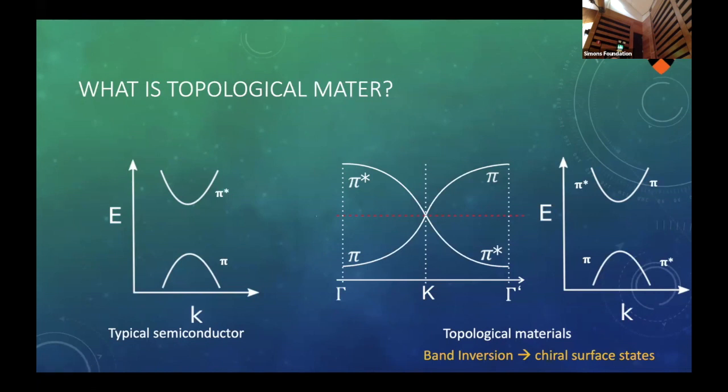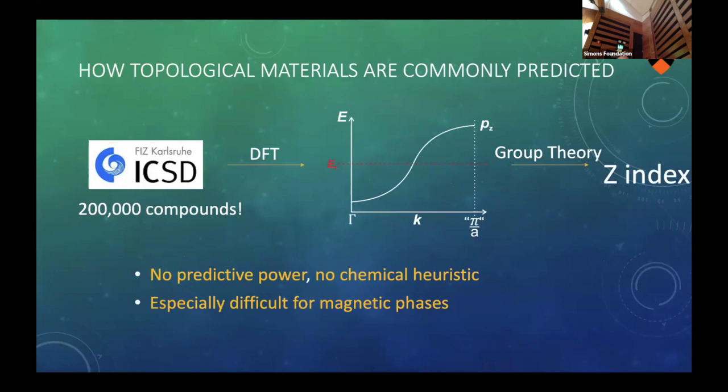And I just want to make sure that for the remainder of this talk, when I define this, I view a band inversion as being the basis for topological materials, because spin orbit coupling can come in later to gap out states and define a topological invariance. But if you have a band inversion, that's the first easy ingredient for a material to be topological. So I will be looking from a chemical perspective at what we can do or make to design materials to have a band inversion.